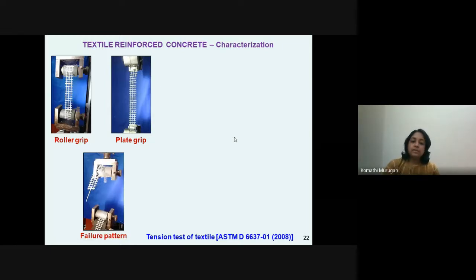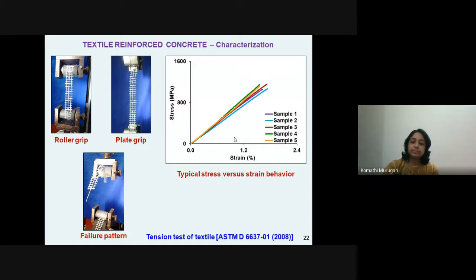So what we typically do is we check the single yarn tensile strength of a textile. So this single yarn tensile strength is extrapolated to the multi-rip strength, and also multi-rip tensile tests are conducted in order to understand the efficiency comparing the single yarn and the multi-rip, and based on this the tensile strength of the textile is ascertained and it is used for design. So typically what we get is the stress strain behavior from the tension test of textiles. What we see here is for 5 samples, we get more or less a behavior like this. There is a certain scatter depending upon the manufacturing process of the textile.